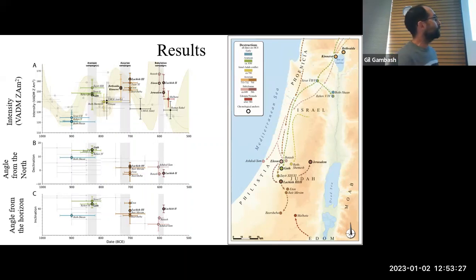And this enabled us to look at the reconstruction of the different military campaigns and correlate between sites that were presumably destroyed during a specific military campaign. And usually, in most cases, as you can see here, like the green points here and others, we have a good correlation between sites that were presumably destroyed during a certain military campaign. Now, there are a lot of chronological conclusions that we mentioned in the paper.